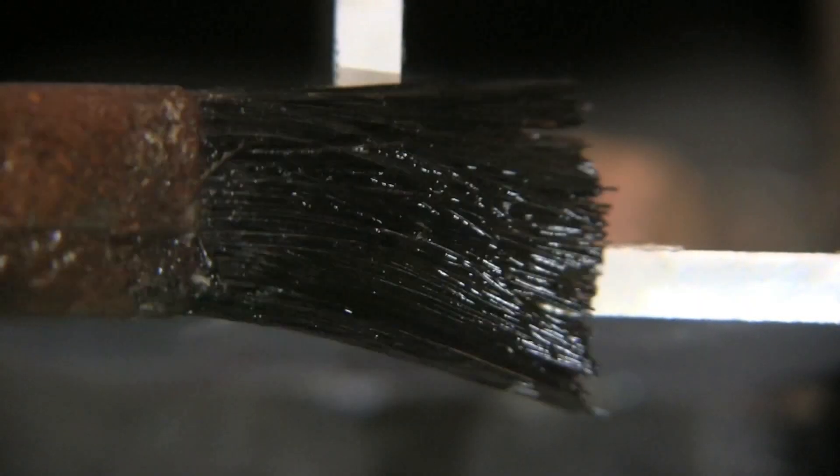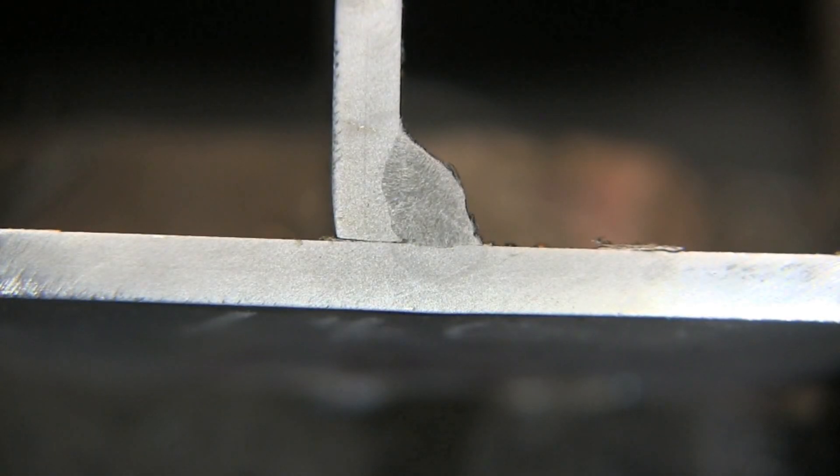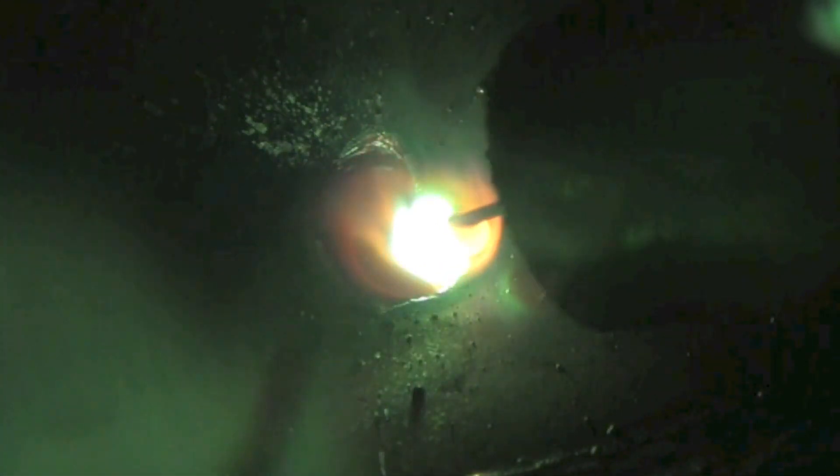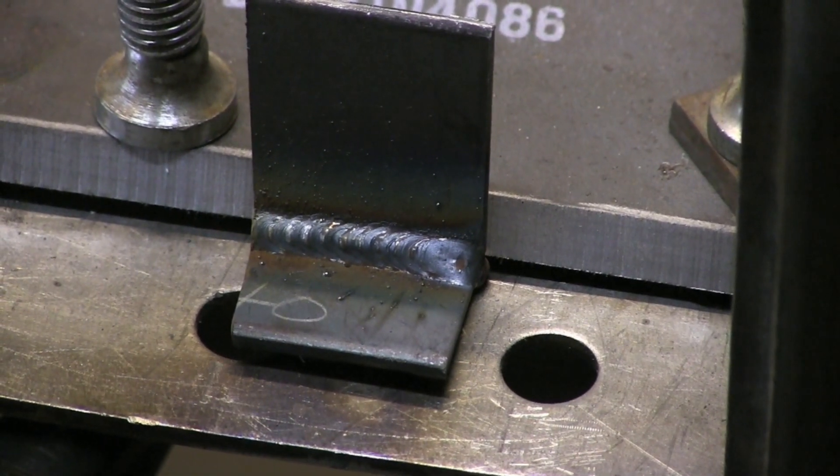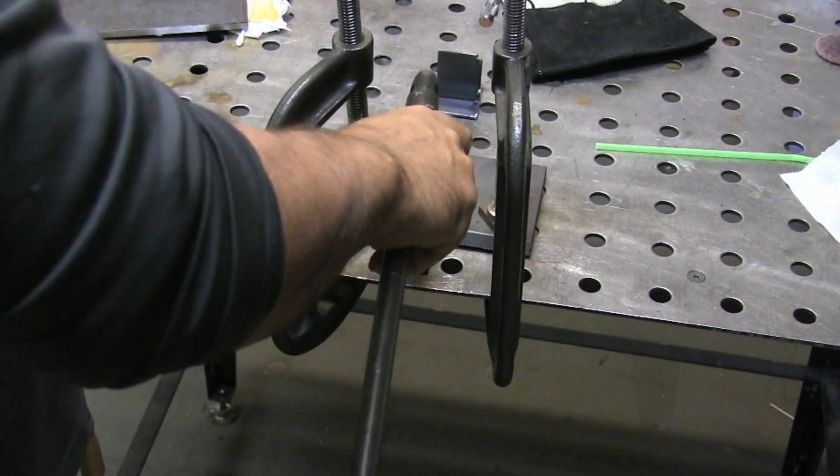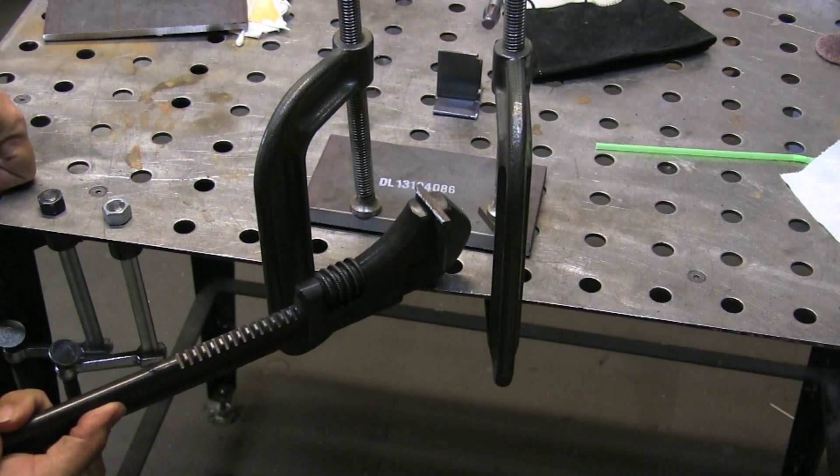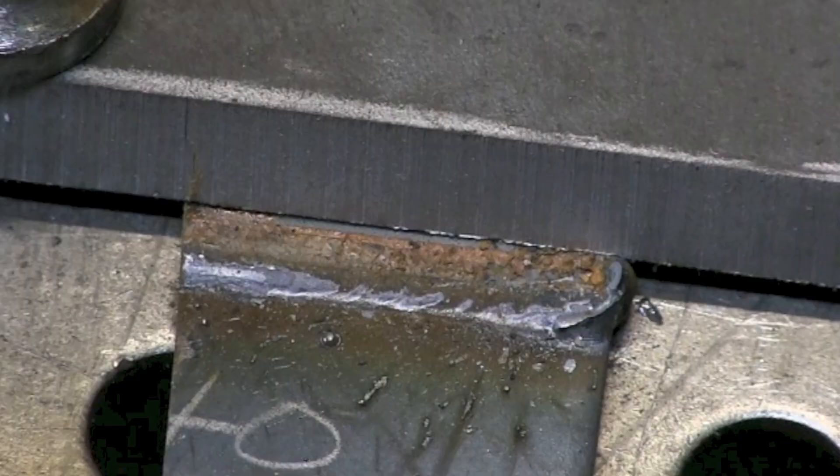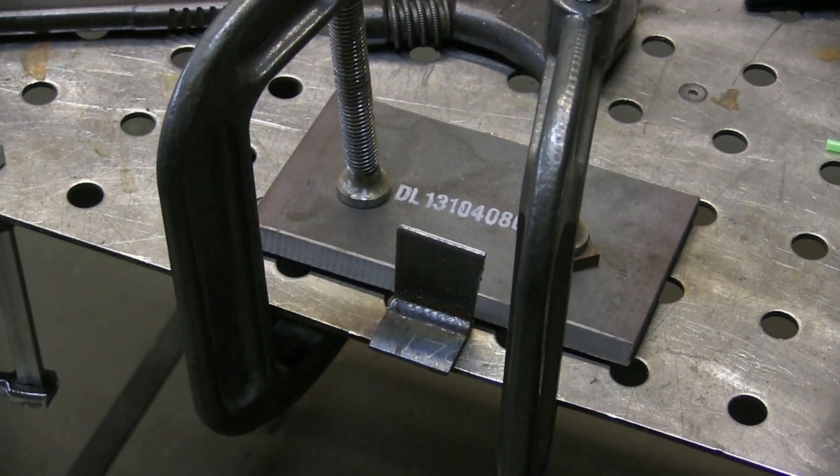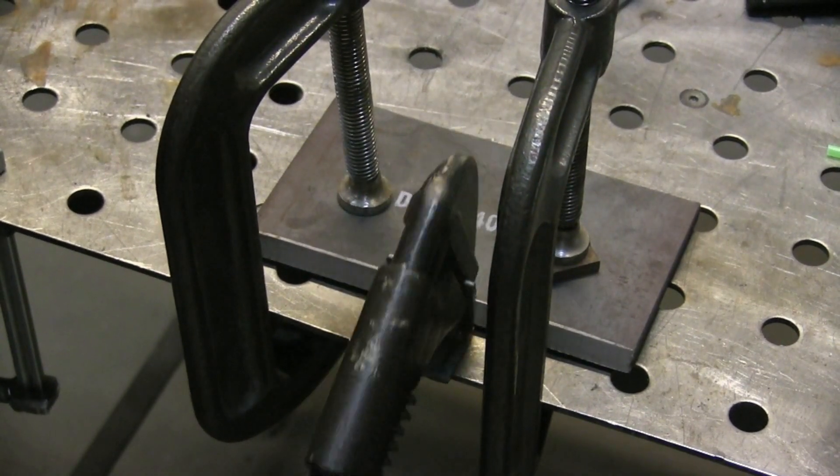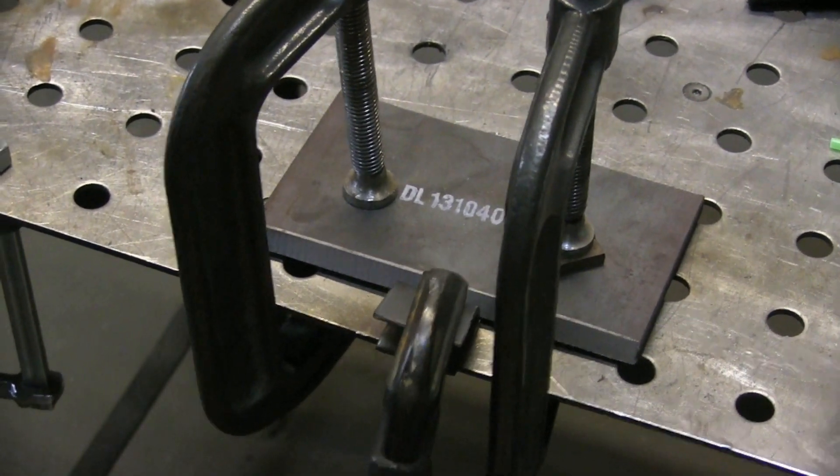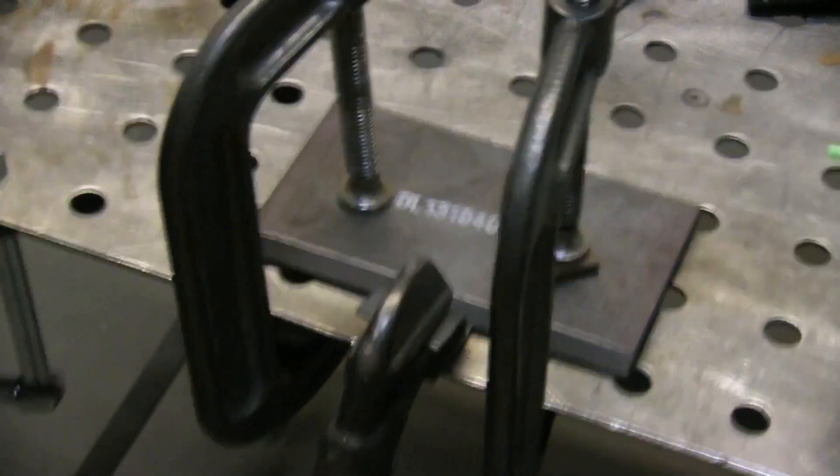Let's go all the way down to 140. Wasn't expecting much out of this and didn't see much either. That laid in there like a bead of caulk on the bottom. Way too low on the wire feed speed. And I decided actually to go ahead and do a break test on this just to prove to myself it was as bad as it looked. So I clamped it down and clamped my big Ford wrench there to it. And with hardly any pressure at all, it just snapped. Didn't even bend the piece before it snapped. Here's a little close-up of how it just hardly even nipped through the hot rolled mill scale of the bottom piece. And I decided also to do the 170 to see if the same thing was true there. But actually the 170 inches a minute held up much better. Bent the piece over and didn't break. Probably could have broke it if I bent it back and forth.